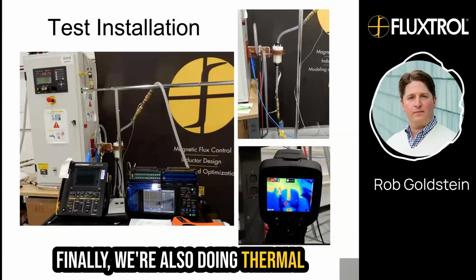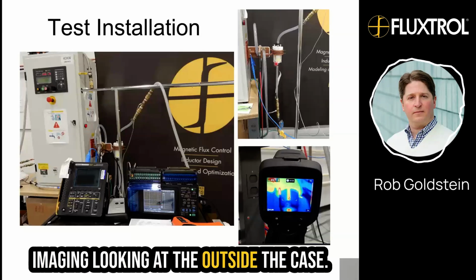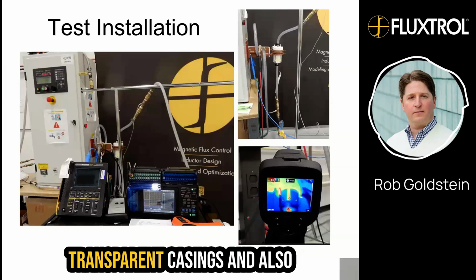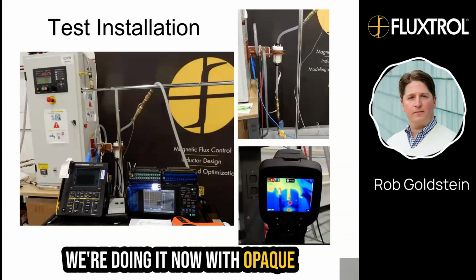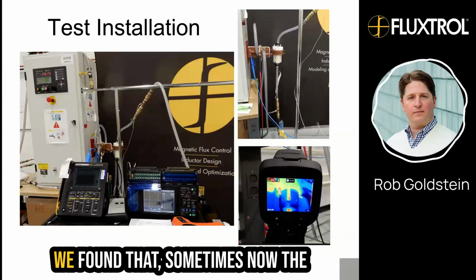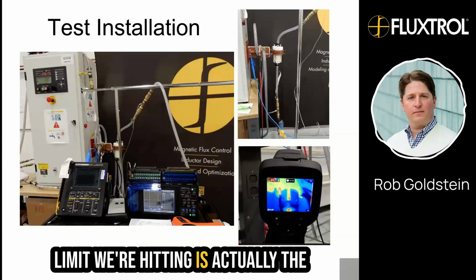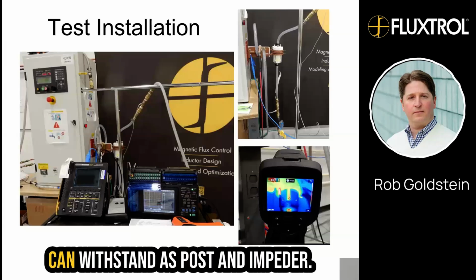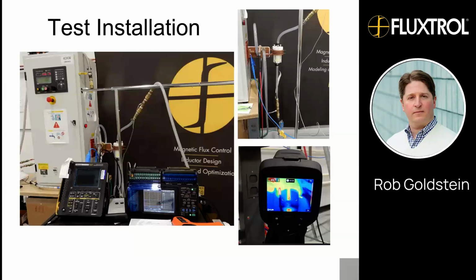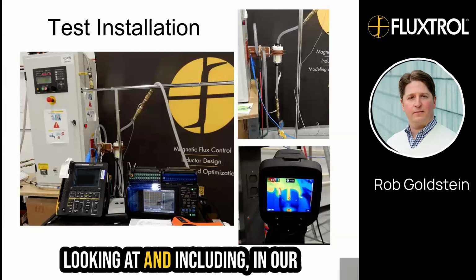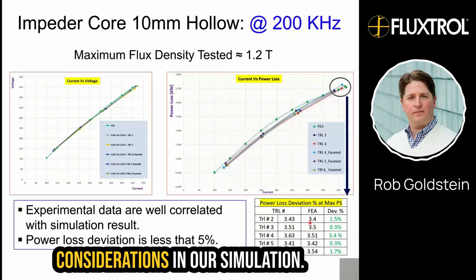Finally, we're also doing thermal imaging, looking at the outside of the casing. We've done this both with transparent casings, and also we're doing it now with opaque casings, which are typical, because we found that sometimes now the limit we're hitting is actually the temperature the impeder casing can withstand as opposed to the impeder. That's another thing that we're looking at and including in our considerations in our simulation.